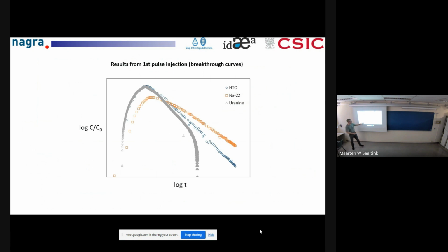in real time, you see how the system is evolving. It's good that we have a very good match between tritium and uranine. They are both conservative. After some time, the detectability of uranine is not so good. At lower concentration, you have problems, so eventually they diverge. We can capture the peak very nicely and the relative concentrations very nicely. That was good, but there are interesting differences between the tritium and the sodium. Clearly you have a lower peak, which is due to sorption; sodium sorbs.